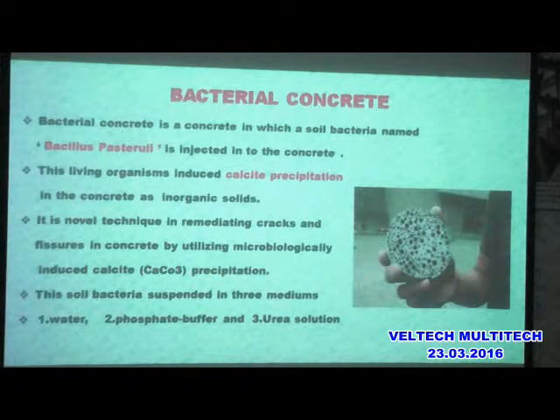So where are we going to use this? For example, in old buildings, the cracks are in the beam. The crack dimension may be 1 or 2 mm. But within that 1 or 2 mm, physically we cannot repair that crack. There what we are going to do is inject this bacteria into the cracks. There that bacteria is going to convert into calcite, such that the calcium is going to be formed within that crack, such that the crack is going to fill, and the concrete is going to be free from that crack, and the load carrying capacity is going to be increased. So like this, the bacterial concrete is going to help us.